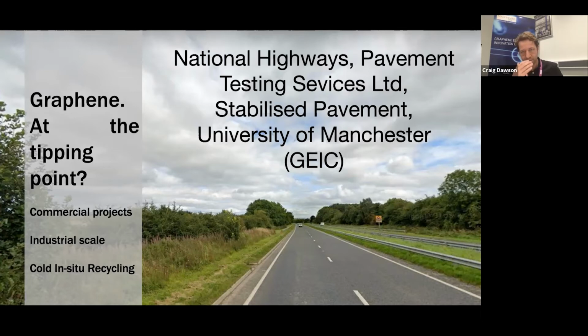We did a lot of laboratory pre-work, and we were seeing in the laboratory stiffness increases of about 25%, which gave National Highways enough confidence to put this material on a live project. And we've got cores that are currently undergoing testing to see the effect that we're having in the field, using the variability of a real road produced using the in situ recycled process. Early indications are that we're matching laboratory performance in the field.